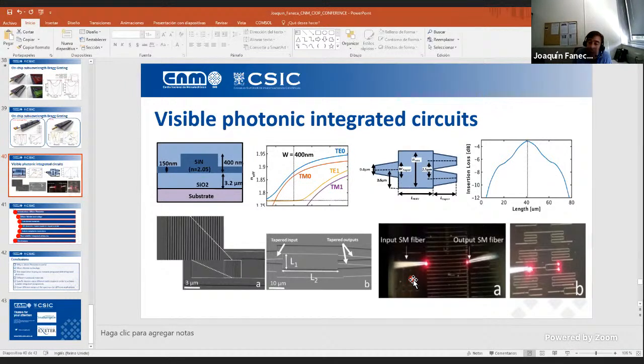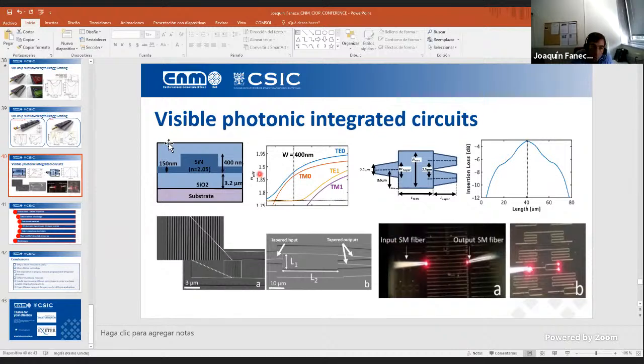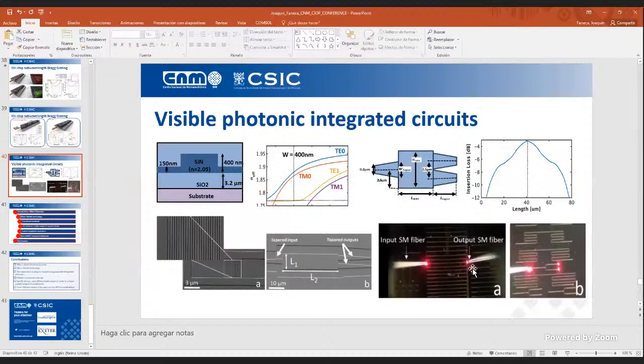So if you talk about a sensor that changes the absorption of the light, we can. What we can do is put a trench on top of these waveguides. Here the cross section is easier. Maybe we create a trench and deposit some molecules. If they absorb in the visible range of optics, you will have a change in the optical power at this output. This change in the optical power will be related to your molecules here. But right now, downstairs, what we can measure is power. So if you are talking about sensing with the optical power, yes, we can try to go for it. If you're talking about phase modulators or biosensors that work with the phase, I think we are not ready yet to have them characterized.